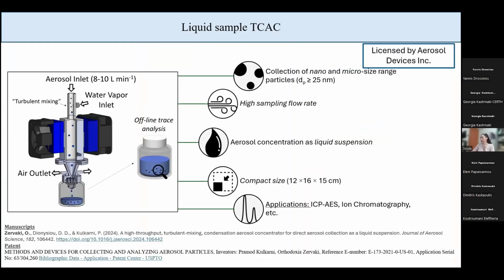So the next study that I worked on had to do with an upgrade of this device. We wanted to achieve higher flow rates. In the previous device, we were working at 4 liters per minute. Now, when you collect droplets on a substrate that you have to heat, you can increase the flow rate, but you will have to increase the temperature of the heated substrate to be able to evaporate the water as quickly as you collect the droplets.